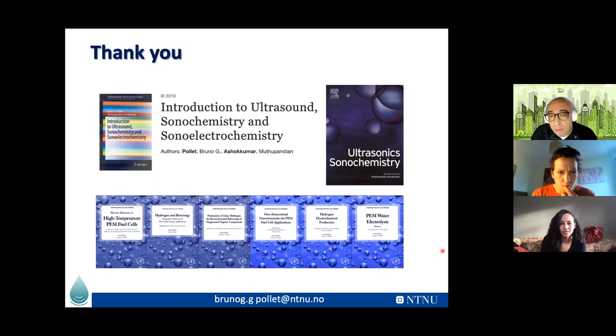In a way, yes. But I must say that sonoelectrochemically, it is much easier, because then you can control galvanostatically the time of pulsation, and also the time of when you want to dislodge that nanoparticle from the electrode. If you play with the sequence of sonication and the current, you could effectively play with your particle size. So electrochemically you can do that very easily, I think.